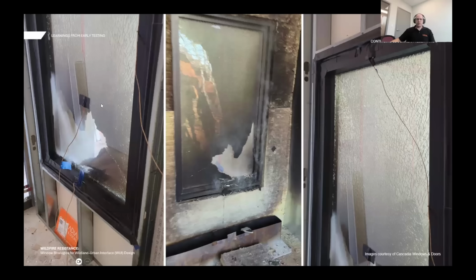And so this is more photos from the back side of that same photo I showed on the right-hand side. The inner pane of glass that is tempered did survive. The outer pane that was tempered in this case cracked about halfway through the test. About 20% of it fell out. The 80% of it stayed in place during the test.